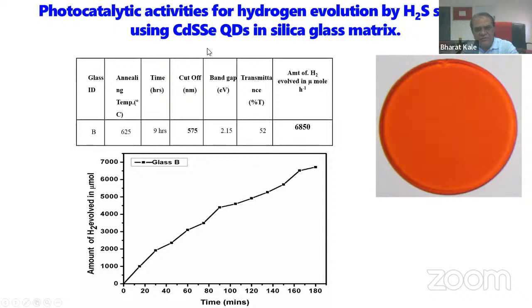Then CdSSe quantum dots in some silica glass matrix, which we observed at large scale. We observe that there is a good photocatalytic activity. We get an amount of hydrogen, you see 6,850, which is only 2,000 micromole in case we have isolated quantum dots without glass.